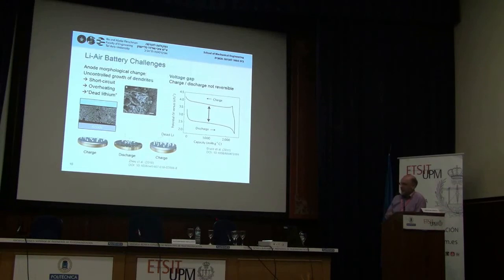But imagine that instead of trying to bring the lithium back to the original electrode, we take the lithium oxide outside, we decompose it thermally, and then we bring back the lithium in a pure form to form a new electrode. And in this case, we don't have this kind of growth because we have liquid lithium somewhere that we can just coat on a surface and produce the electrode. And if we keep the entire battery at this temperature above 180 degrees, then the lithium is liquid anyway. We don't need a solid electrode. And of course, if we charge thermally, then overvoltage is not a question. So we can eliminate these fundamental problems if we are able to charge the battery thermally.